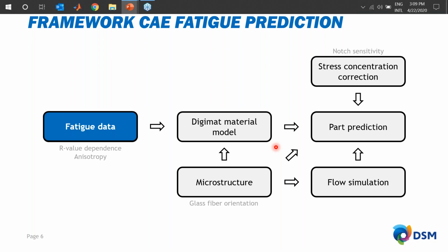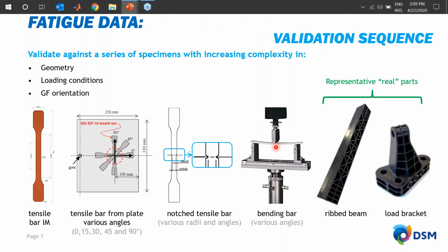So first, the fatigue data. What we want to do is build up a certain validation sequence. So instead of just measuring, let's say, the R value dependency and anisotropy and then trying to do a part prediction, we want to really understand where we do well and where we do wrong. That means we want to validate against a series of specimens while we gradually increase complexity in geometry, loading conditions, and fiber orientation.